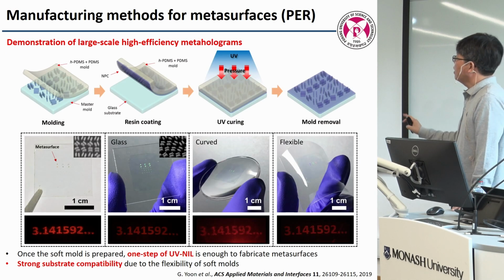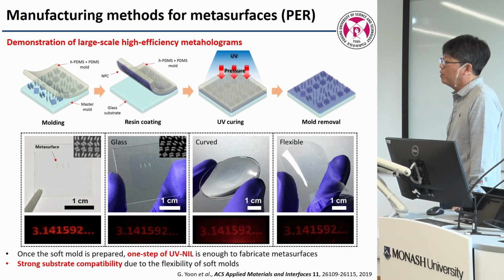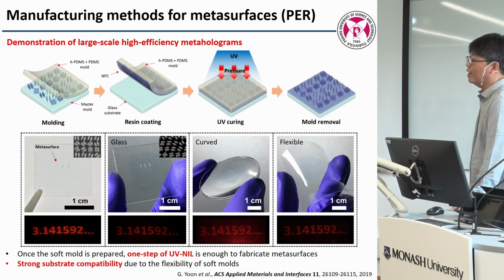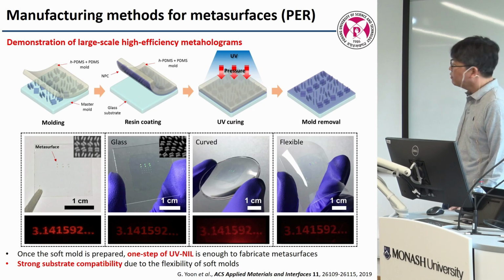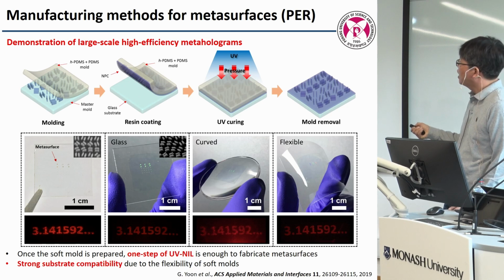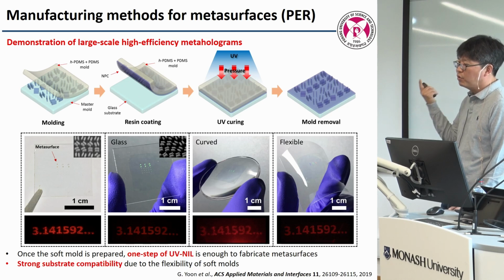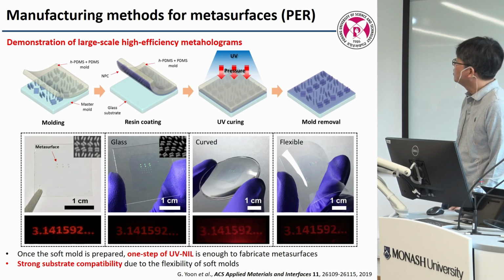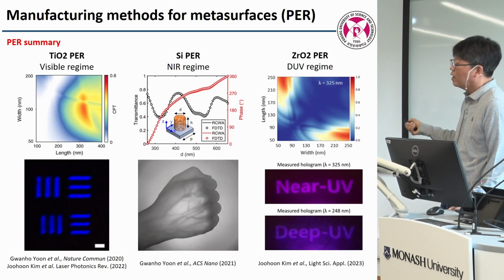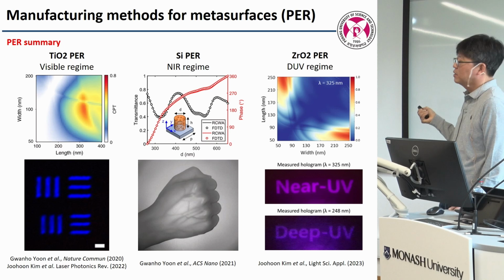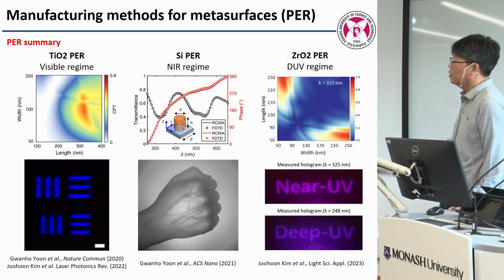And another thing we developed is a nano-imprintable, very high index polymer. Usually nano imprinting uses polymer, but polymer has a 1.5 refractive index, so it is not good enough for phase control. But we added functional nanoparticles inside, so the index goes to 2.5, 2.2, and then it can work similarly to TiO2. Some of the candidates are silicon nanoparticle embedded resin in IR, zirconium oxide in deep UV, and TiO2 nanoparticles in the visible. So we can assume this is just TiO2, and zirconium oxide is a thin layer. So that's one thing, imprintable.